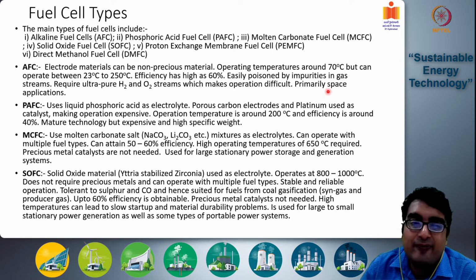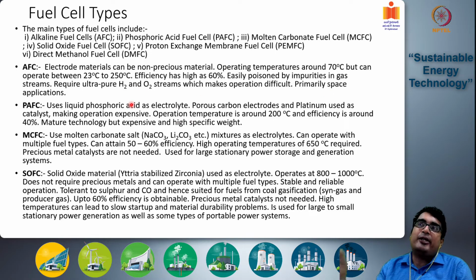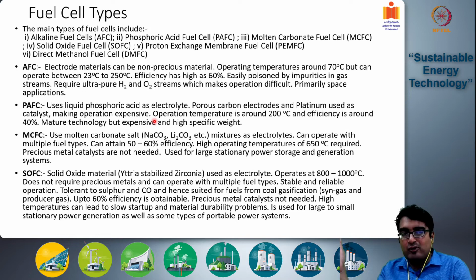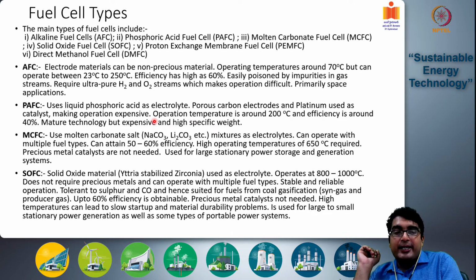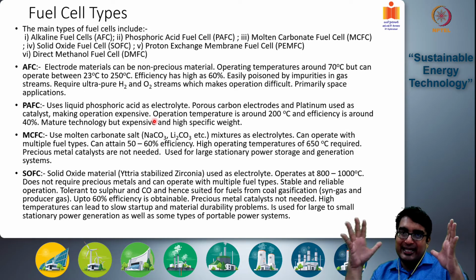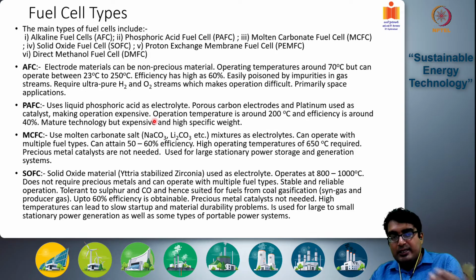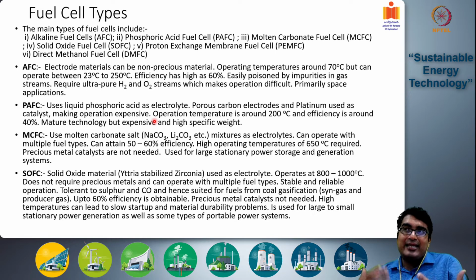Then you have phosphoric acid fuel cells. So here, as the name implies, instead of potassium hydroxide, it uses an acid, a phosphoric acid, H3PO4, if I remember correctly. The electrodes are porous carbon, and platinum is used as a catalyst coating the electrodes, which makes the operation expensive. Operating temperature is around 200 degrees centigrade, so it is a heated fuel cell, and efficiency is around 40%. So efficiencies are low also. It's a mature technology, but is expensive and has high specific weight. So the weight requirement is also quite high because it is using carbon electrodes and platinum primarily. A liquid phosphoric acid electrolyte, and it has a high operating temperature and reasonably low efficiency as well.